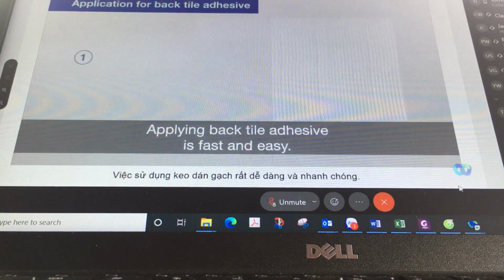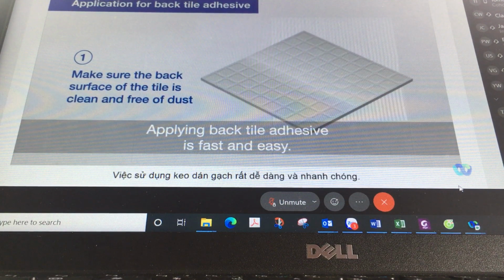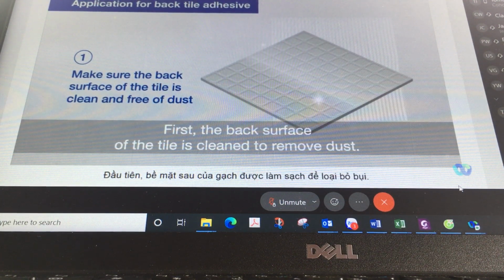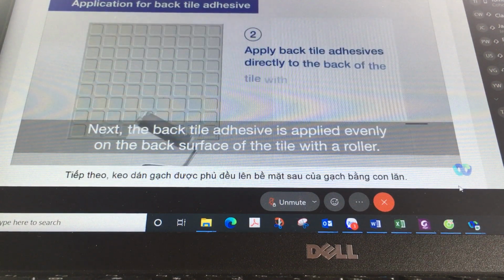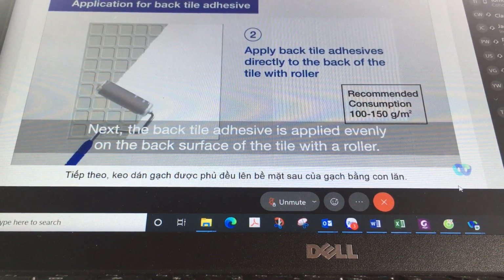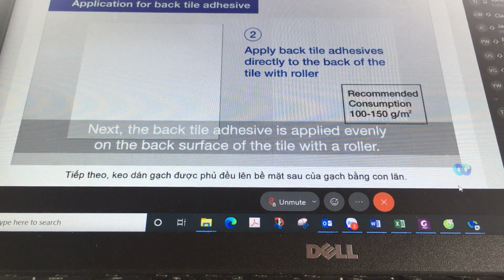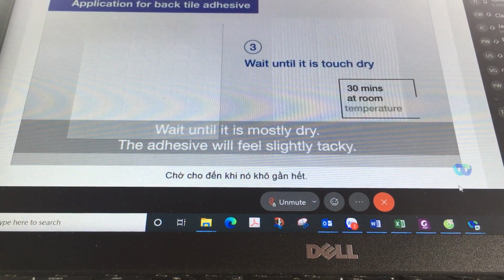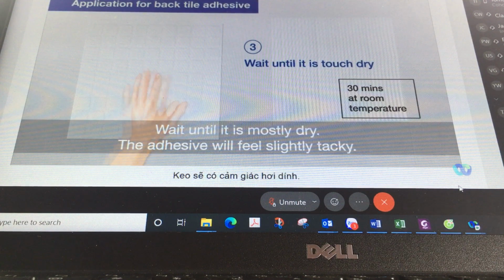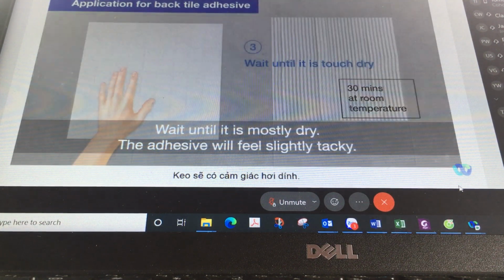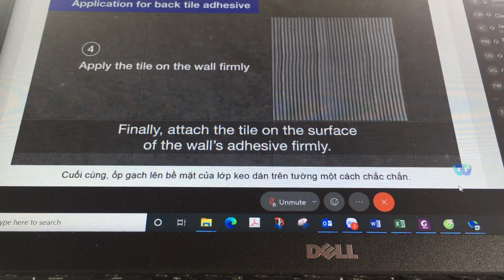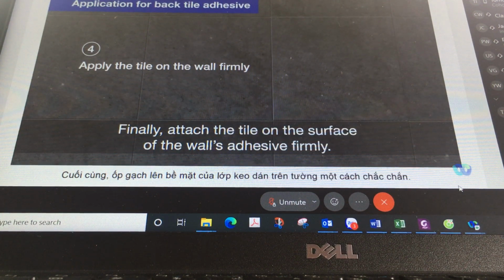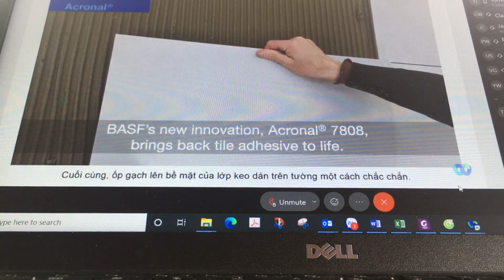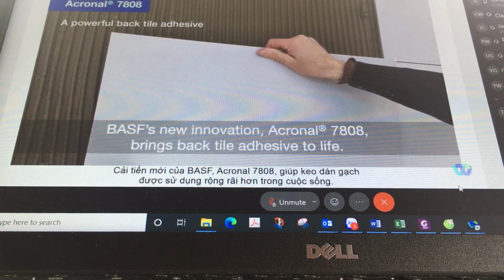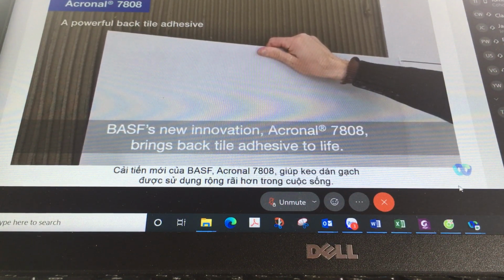Applying back tile adhesive is fast and easy. First, the back surface of the tile is cleaned to remove dust. Next, the back tile adhesive is applied evenly on the back surface of the tile with a roller. Wait until it's mostly dry. The adhesive will feel slightly tacky. Finally, attach the tile on the surface of the wall's adhesive firmly. BASF's new innovation, Acronal 7808, brings back tile adhesive to life.